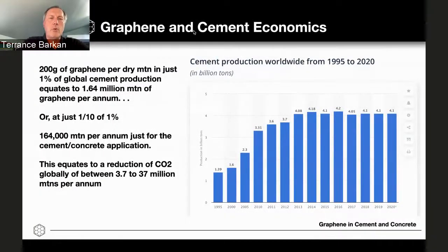200 grams of graphene per dry metric ton in just 1% of global cement production is 1.64 million metric tons of graphene. So even at just 0.1% market penetration globally is 164,000 metric tons per annum just for this one application. And it would take out between 3.7 to 37 million metric tons of carbon per annum. So again, this is an example. If graphene is seen as a viable ingredient, even at an incredibly small penetration rate, we need enormous volumes. And so that's the interesting pull.